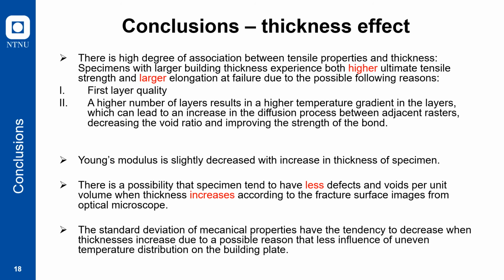And for that, we can get some conclusions. First, there is a high degree of association between the tensile property and thickness. So in detail, specimens with larger building thickness experience both higher tensile strength and larger elongation at failure due to possible reasons. First, layer quality, because for 3D printing, especially FDM, the first layer is really important to print and to optimize, and sometimes it can be affected by many other factors. So there's uncertainty in first layer quality.